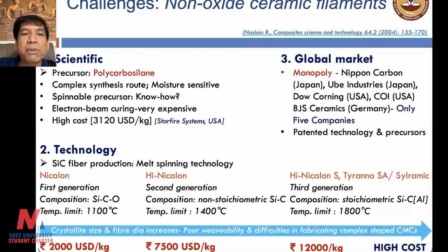Just to give you an idea, for example, if you want to purchase polycarbosilane from United States of America, there's a company called Starfire Systems, and they charge like $3,120 per kg to purchase them. There are only a few companies which can make them. For example, Nippon Carbon in Japan, Ube Industries in Japan, Dow Corning in USA, and again COI in USA, and BJS Ceramics in Germany. Only 5 companies can make these kind of fibers, because they're all patented and technologically very challenging. And if you want to really look at the costs involved to purchase 1 kg of silicon carbide fiber, depending on the quality of silicon carbide fibers per kg, it can vary from $2,000 to $12,000.